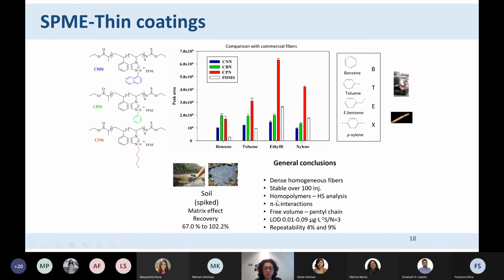The fiber was also stable over 100 injections. And we think that this happened through pi-pi interactions. And although it might seem very strange, these two polymers, the one that has the benzyl group and the naphthyl group, do not have as much interaction with our compounds because we think that they interact among themselves. And so they are very dense and they do not allow the compounds to penetrate.